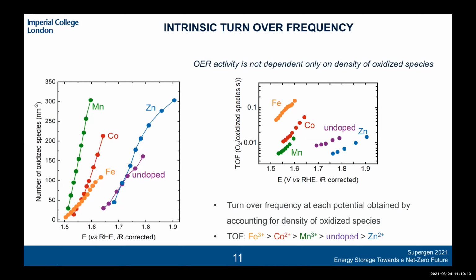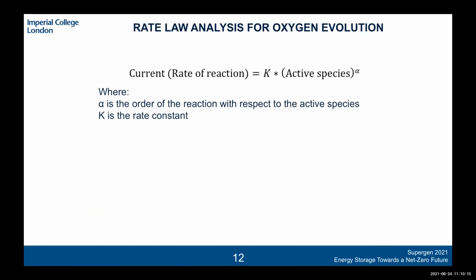And in order to then try and understand why we have these trends as a function of dopants, what we can do is perform a rate law analysis. So quite simply, a rate law analysis relates the rate of a reaction, which is the current in this case, to the density of the active species. And the active species are raised to the power of alpha, where alpha is then the order of the reaction with respect to these active species.